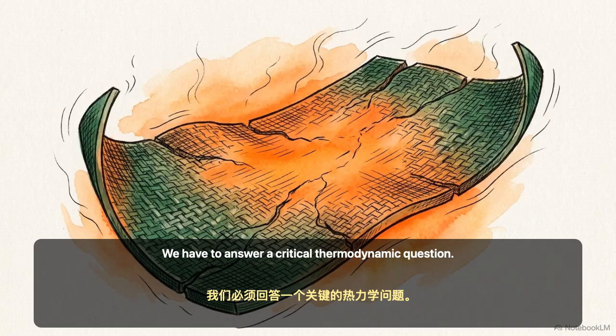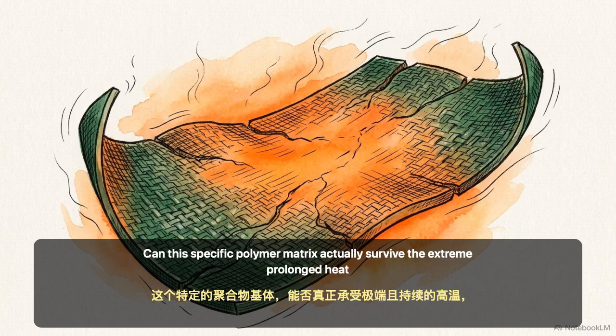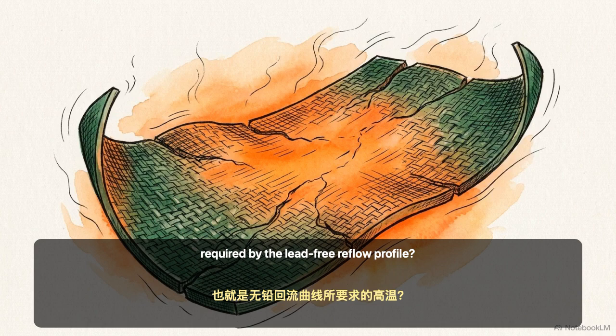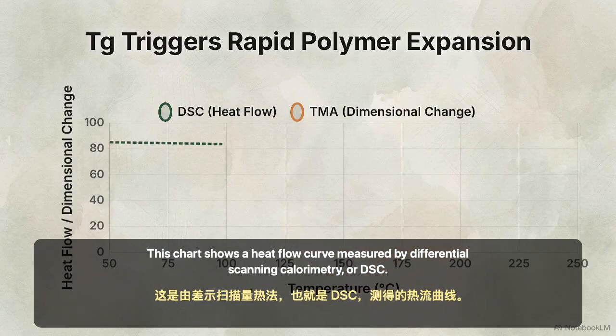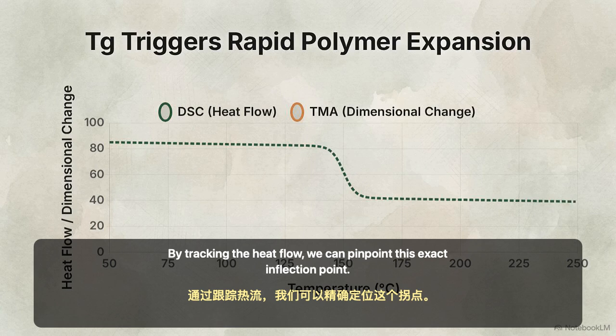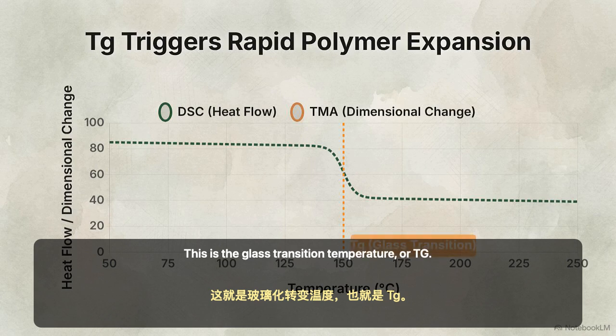We have to answer a critical thermodynamic question. Can this specific polymer matrix actually survive the extreme prolonged heat required by the lead-free reflow profile? This chart shows a heat flow curve measured by differential scanning calorimetry, or DSC. By tracking the heat flow, we can pinpoint this exact inflection point. This is the glass transition temperature, or TG, the moment the polymer begins to soften.